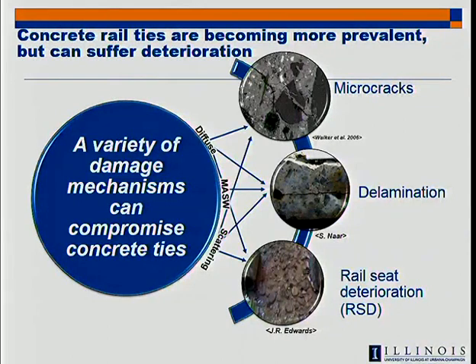And concrete is a large-scale composite material, quite chemically stable and thermally stable, a fantastic material, but it does degrade. It has problems. Like wood, when it's exposed to moisture and the environment and oxygen and loads, it will degrade. And often these mechanisms are coupled. It's not one mechanism by itself, but freezing and thawing action and chemical reactivity of groundwater work together to start deteriorating these things, or problems with the original aggregates can cause ASR and DEF problems with processing. All of these things can occur in concrete ties, and very often they manifest themselves as distributed microcracking.